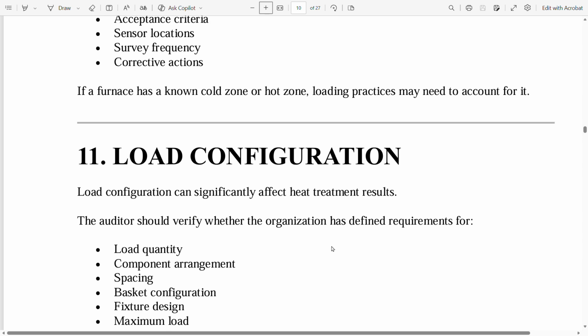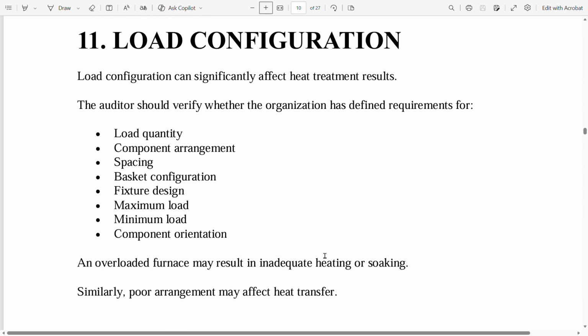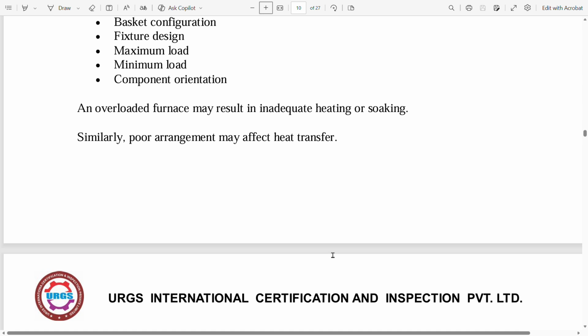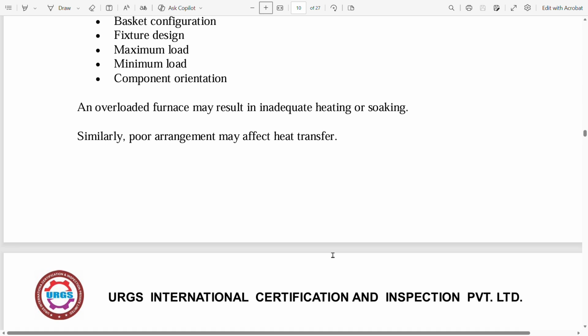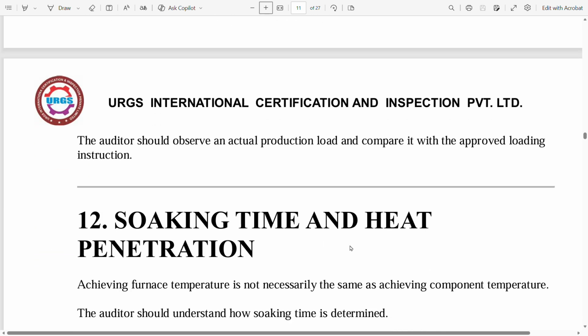Now, load configuration. Load configuration can significantly affect heat treatment results. The auditor should verify whether the organization has defined requirements for load quantity, component arrangement, spacing, basket configuration, fixture design, maximum load, minimum load, component orientation. An overloaded furnace may result in inadequate heating or soaking. Similarly, poor arrangement may affect heat transfer. The auditor should observe an actual production load and compare it with the approved loading instructions.